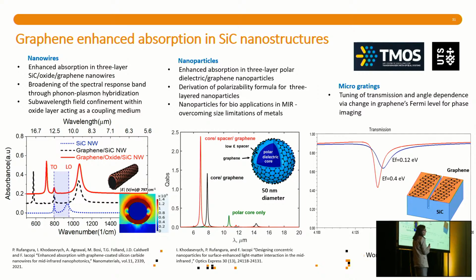Now, an interesting thing is that when you couple that with the graphene, so when you cover that nanowire with graphene, all of a sudden this mode splits because of the coupling. So we have an M1 and M2, but it not only splits, it extends outside of the Reststrahlen band, which is the colored part here, and it has higher absorption in the IR, which is really, really interesting.